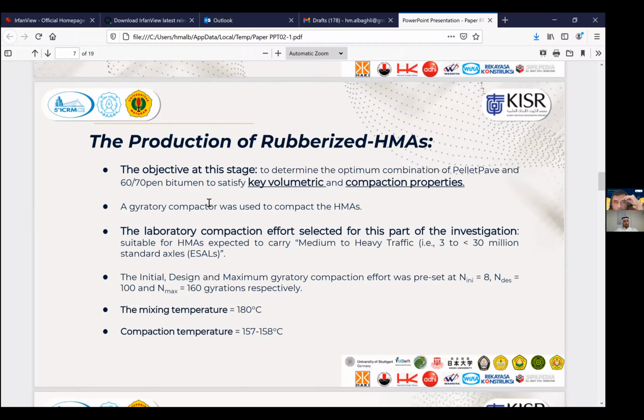In order to do that, we used a gyratory compactor to compact the rubberized hot mix asphalt blends. The compaction effort was selected as suitable for a route expected to carry medium to heavy traffic. As you can see here, the initial, design, and maximum gyratory compaction efforts were preset at N-initial 8, N-design 100, and N-max 160 gyrations respectively. The mixing temperature was 180 degrees Celsius and the compaction temperature was 157 to 158 degrees Celsius.